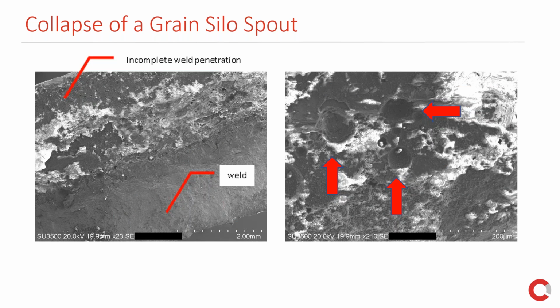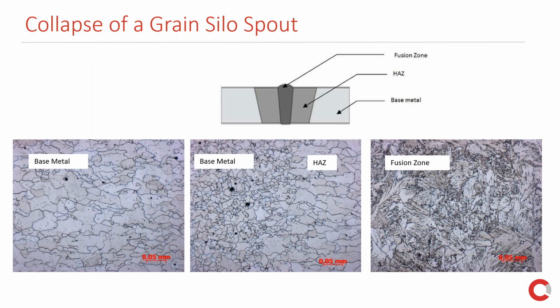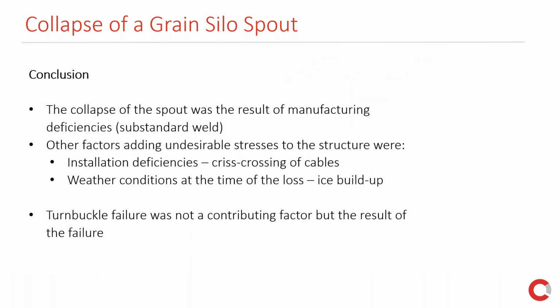The weld was further examined under a scanning electron microscope, and deficiencies that were observed earlier were confirmed. Further metallurgical examination was conducted on the weld itself, and it showed that the microstructures were appropriate.